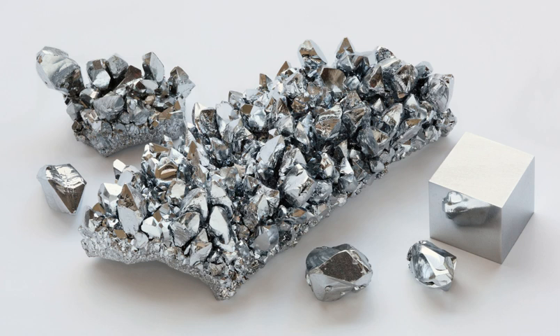Chromium, unlike such metals as iron and nickel, does not suffer from hydrogen embrittlement. However, it does suffer from nitrogen embrittlement, reacting with nitrogen from air and forming brittle nitrides at the high temperatures necessary to work the metal parts.